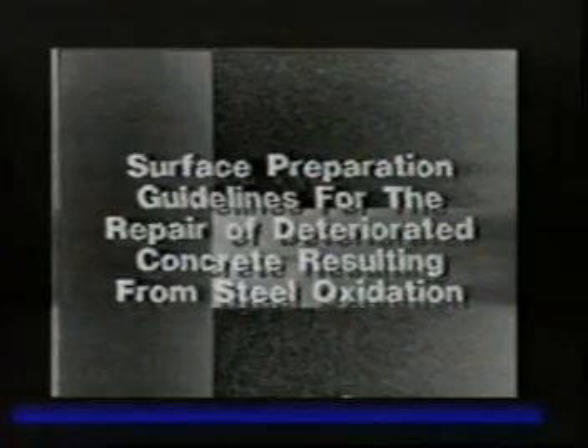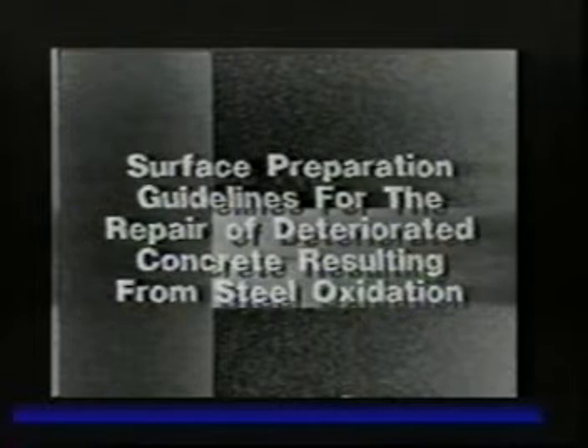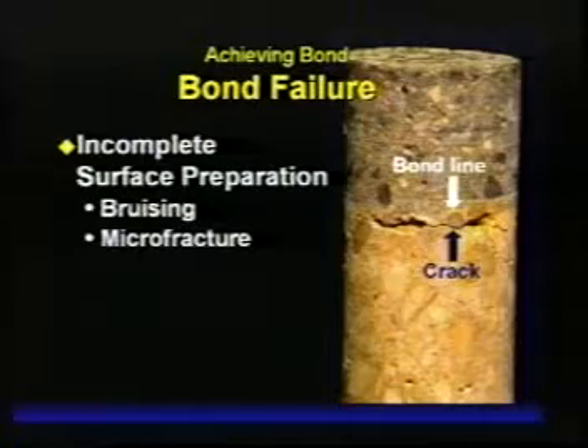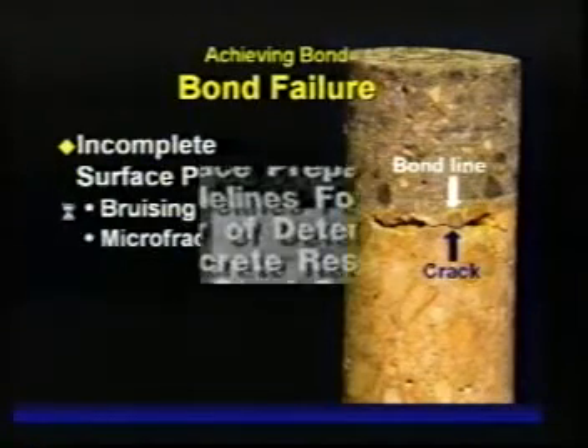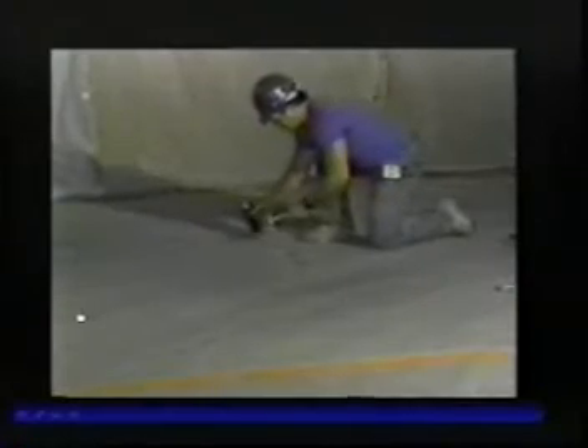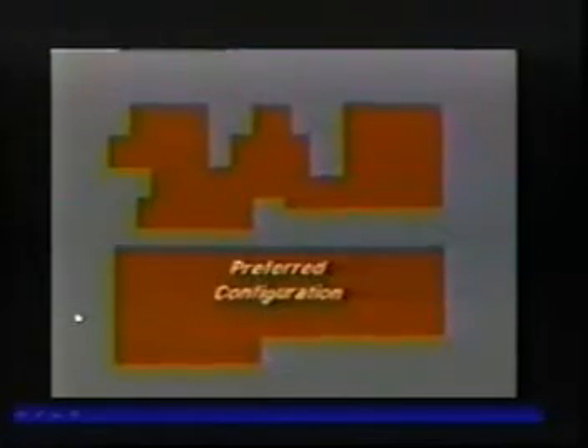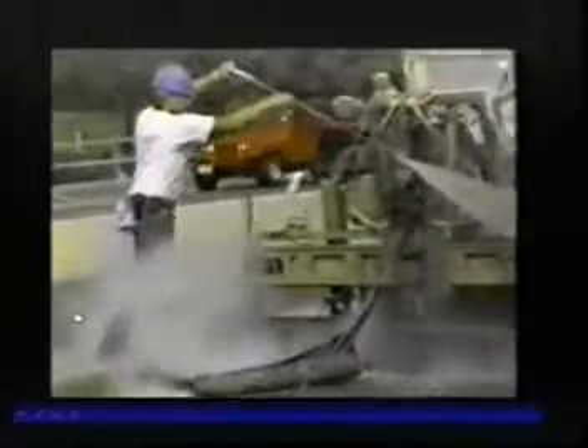This is an excerpt from the ACI video, which is based upon the guideline that was produced in 1989, and this is a shortened version of it without the sound. Certainly the first step, it doesn't matter if it's horizontal, vertical, or overhead, is to lay out the repair work. It's very important to lay out simple configurations. Complex configurations like you see on the top there actually cause a lot of problems and generate a lot of extra cost. The preparation and removal process is either by hand removal with power pneumatic chipping hammers or hydro demolition.